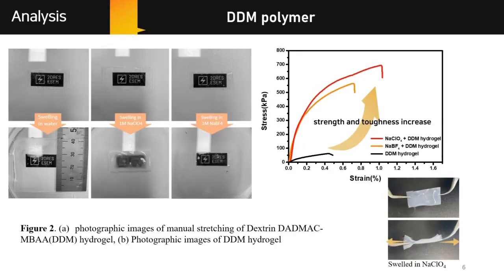I would like to explain the characteristics of the DDM gel when soaked in aqueous electrolyte on this page. When the DDM gel was soaked in DI water, the area increased more than 16 times, but mechanical properties significantly decreased. When the DDM gel was soaked in NaClO4 or NaBF4, the area of the gel shrank a little, but mechanical properties were significantly improved.